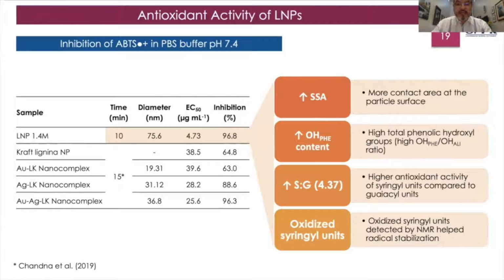The reasons for such a high antioxidant activity are that these particles have a very high specific surface area, a high total phenolic hydroxyl content, and with that also a good ratio between phenolic and aliphatic hydroxyl groups. The syringyl to guaiacyl ratio was also high, and syringyl units are known to be better than guaiacyl units for that specific purpose. And finally, we observed by NMR some oxidized syringyl units, and those syringyl units, due to their higher oxidation level, helped the radical stabilization and therefore leading to higher inhibition performances.